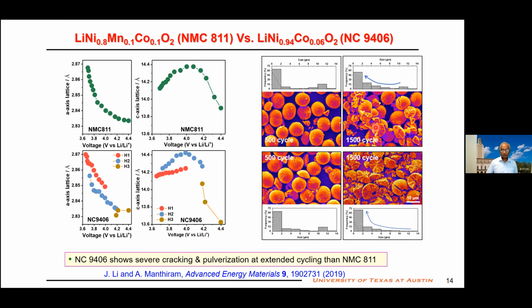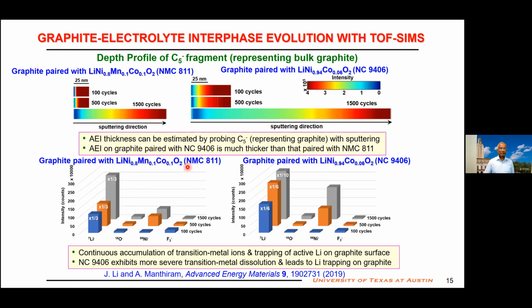The cracks by themselves may not be too much of a problem, but when you have cracks, you create new surface. The surface reacts with the liquid electrolyte to create a lot of unwanted side reactions. So we have done a lot of time of flight secondary ion mass spectrometry, as you see here, with the cycled electrodes. Two cells, one was made with 80% nickel, another one 94% nickel. Everything else is the same. Then after 1500 cycles, we open the cell and analyze the graphite anode. That was the same in both cells, but they were paired with different cathodes. We take the graphite anode and analyze.